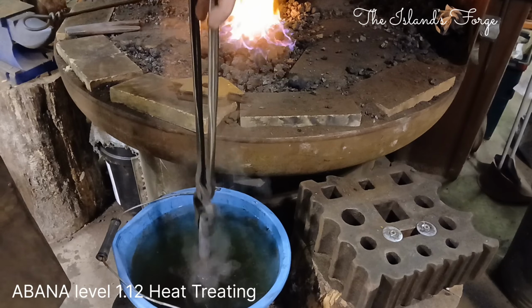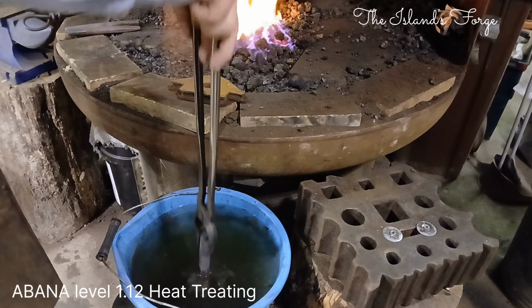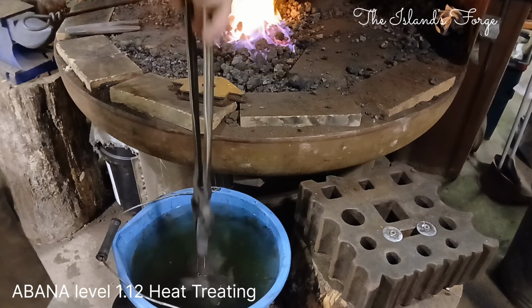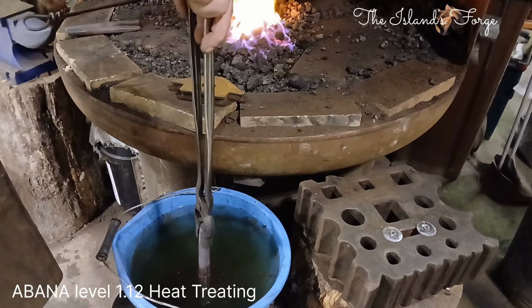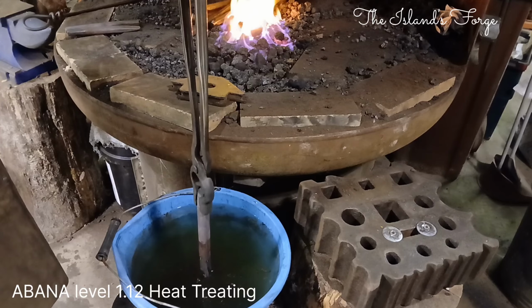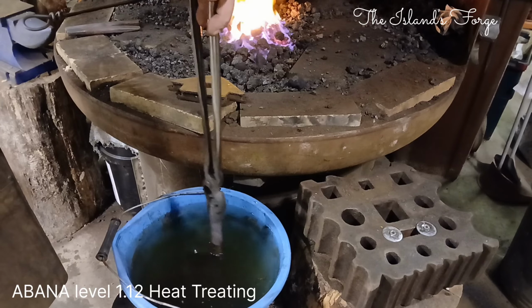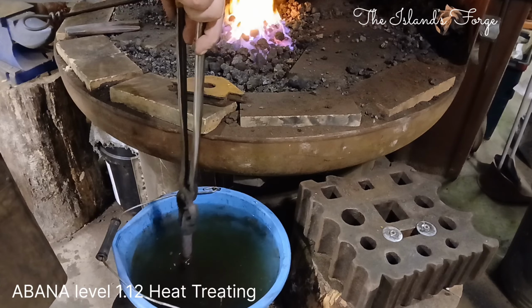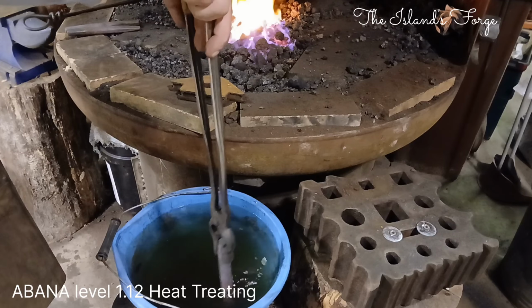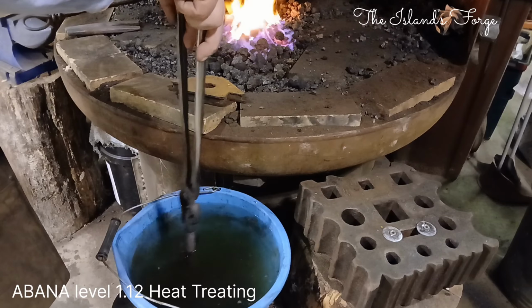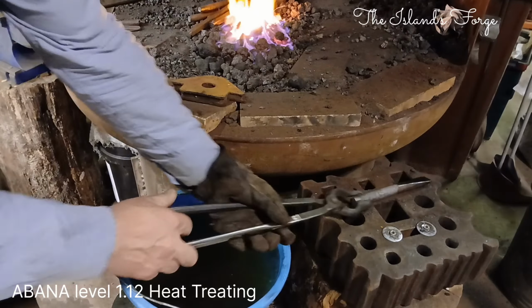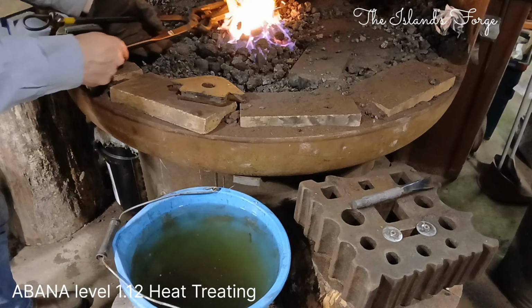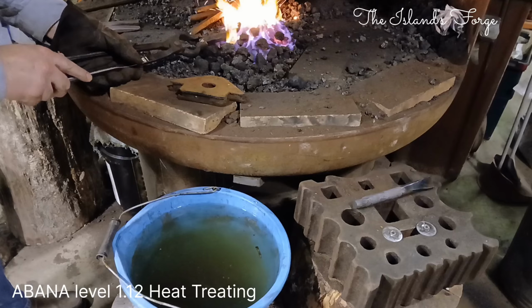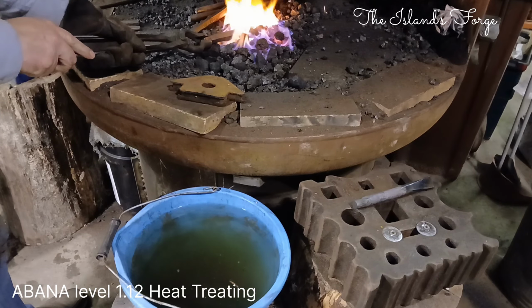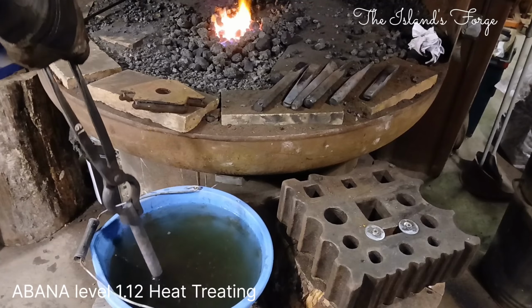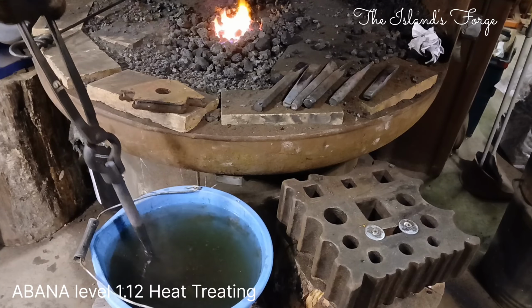So the tongs is holding the hammer end of the tool, which was annealed. We didn't affect that. Heating it a bit doesn't affect anything, which is only if you get it up into the austenite, which is the non-magnetic, the high red, low orange kind of colour. So again, I want to make sure to keep that there a while so that it doesn't lose its temper with the heat. If the main body of the tool still had a lot of heat, it could travel up along the tool and do more than just tempering. Could lose its temper then and soften it.